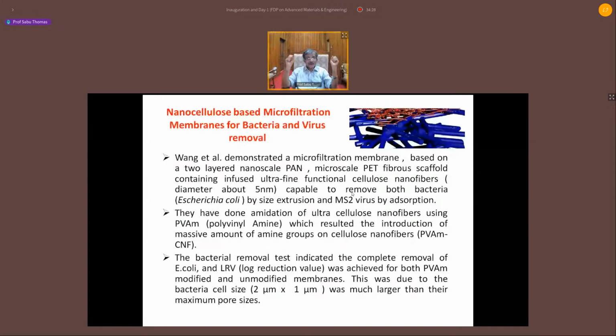But viruses are small. If you want to remove virus, again you have to do a small chemistry. You react with polyvinylamine, as I mentioned. So you introduce a large number of amino groups on the surface of nanocellulose. So you get positive charge. And you all know that viruses have a protein envelope which is negatively charged. And there could be electrostatic interaction between the virus and the membrane, so you can remove that. You can remove viruses. You can remove bacteria. Only thing is you have to properly do a good chemistry.